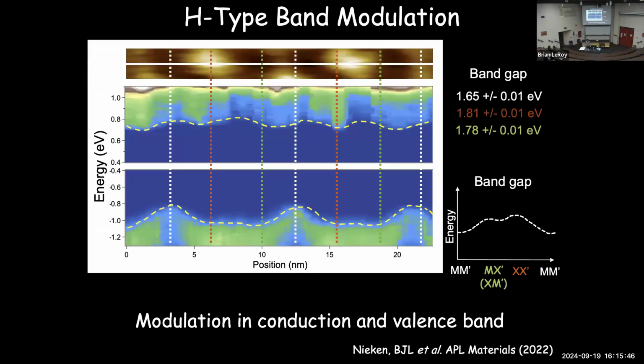And now if we look at the band modulation in this material, we're looking at the conduction band up here and the valence band down here. What you'll notice is that there's a fairly strong modulation in the band gap as a function of position in this material. Basically, the band gap is the difference between the yellow line here and the yellow line here. So it's a small band gap here, larger as we go here, it gets smaller, larger. And so there's this modulation that occurs.